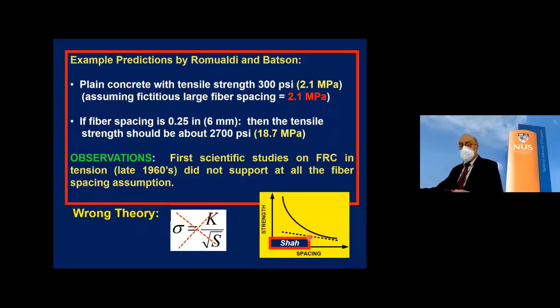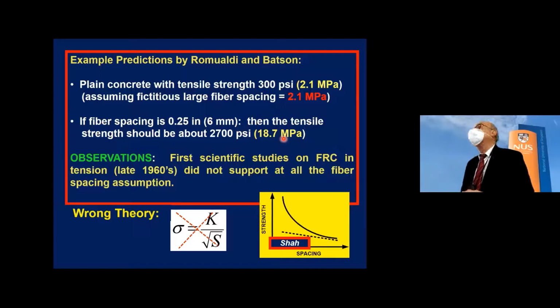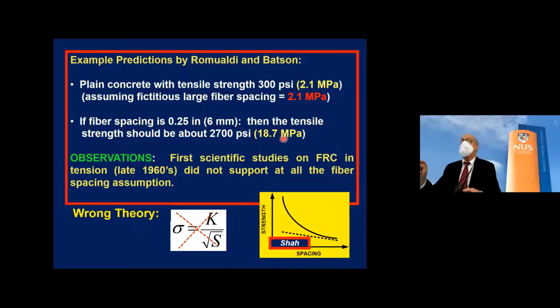So in the 1960s, if you took this new publication by Dr. Romualdi and applied it to plain concrete, let's say, with a strength of 2.1 megapascal, and then added, I can't remember the exact volume, fibers in such a way that the spacing of the fiber is 6 millimeters, it told you your strength in tension increases to 18.7 megapascal. Now, let me tell you, this was very exciting for a lot of researchers, because if we can get concrete at 18.7 megapascal in tension, we can use it without reinforcement. You know, it's a structural material.